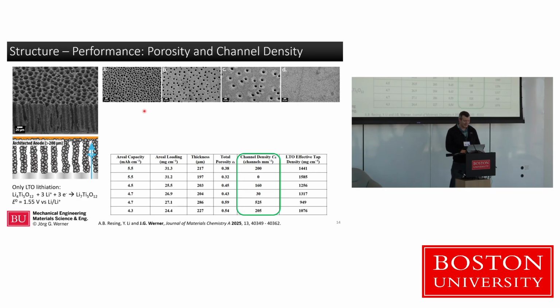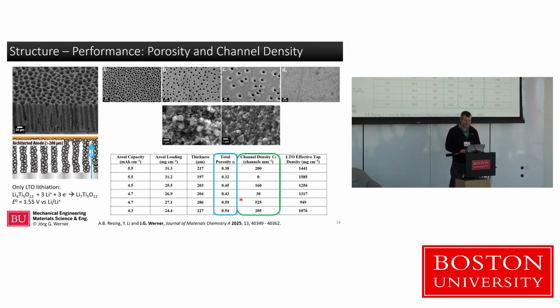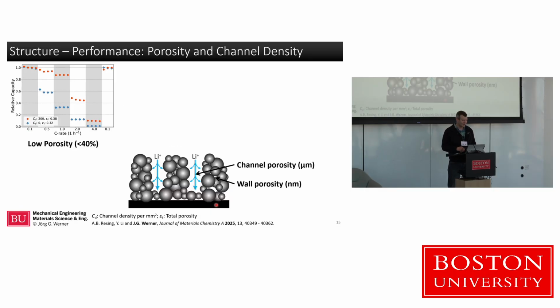We're pretty happy that we can do a lot of these tunings here of different channel densities. That's what we show here, of different wall porosities, which impacts together with the channels how much total porosity we have. The porosity in these different electrodes is just shuffled a little differently between the channels and the interparticle porosity. And we can look at what the effect is. So the way we classified these was essentially looking always at 2 electrodes that have approximately similar porosity, like between 30 and 40% overall, but one of them has no channels in this case, and one of them has 200 channels per square millimeter.